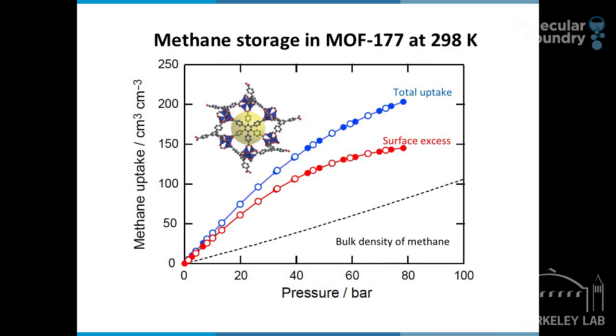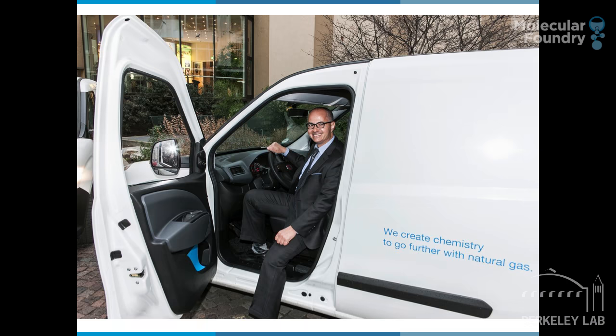Let me give you an example of why this is very exciting. The dotted line illustrates the amount of natural gas that would go in the fuel tank without the MOF. And the blue line is the amount of gas that would go in the fuel tank with the MOF in it. You can see very clearly that, let's say at 60 bar, you can store at least double the amount of natural gas in the fuel tank when the MOF is there, which means that the MOF is acting, as we have expected, to compact the gas molecules closer to each other than they are in the gas phase. This is very exciting because that means an automobile can travel double the distance before it has to refuel compared to today's technology. So in the next couple of years, more and more natural gas fueled cars with MOF tanks will be in the market.